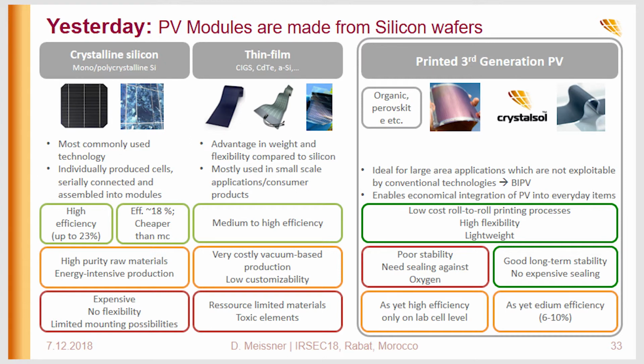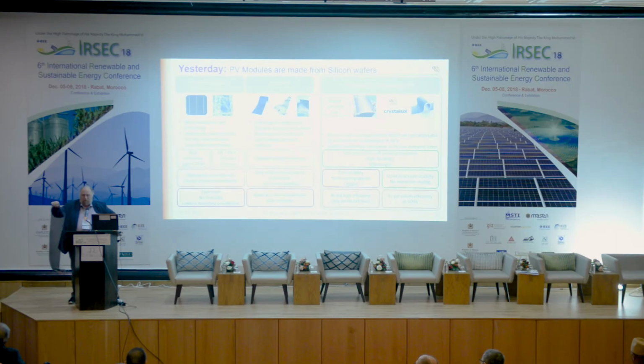Of course, we can discuss about comparing different materials, and of course, one of the most promising new materials are the perovskites. In my opinion, perovskites, but we have more experienced people here, are not really stable in the presence of oxygen. So most tests are done in glove boxes or so. But if you expose them to oxygen, it becomes a problem with the stability. Our material is stable without sealing. Okay, so we have it 3,000 hours at 85 degrees. As long as there is no water, it's stable.